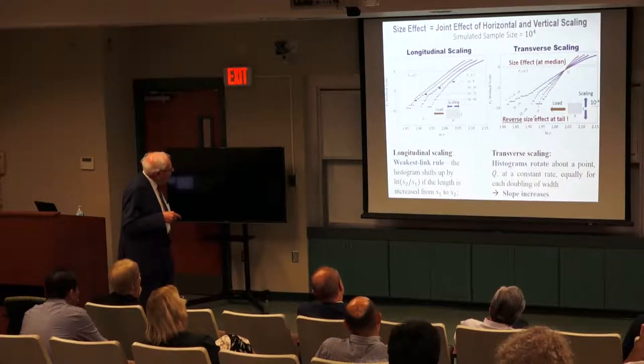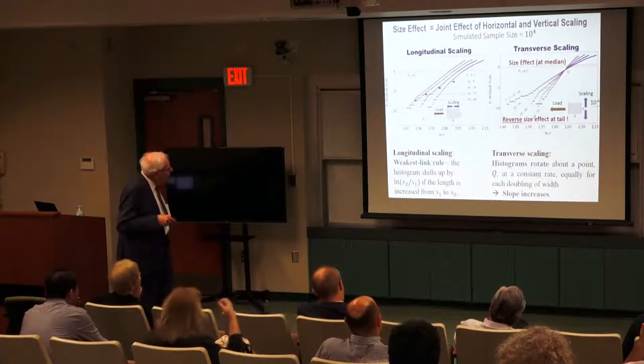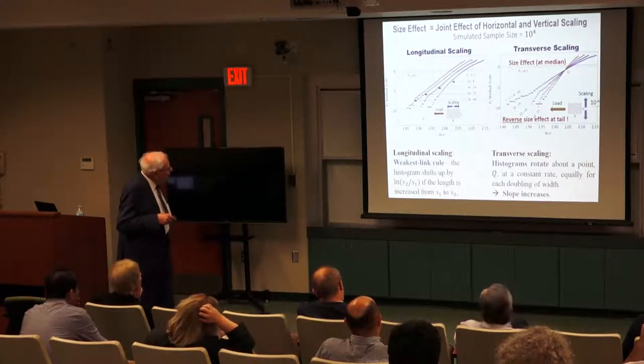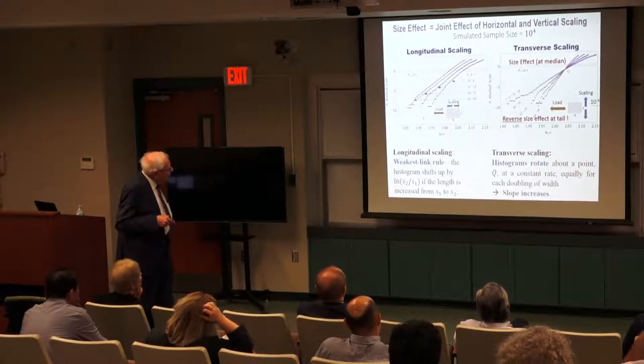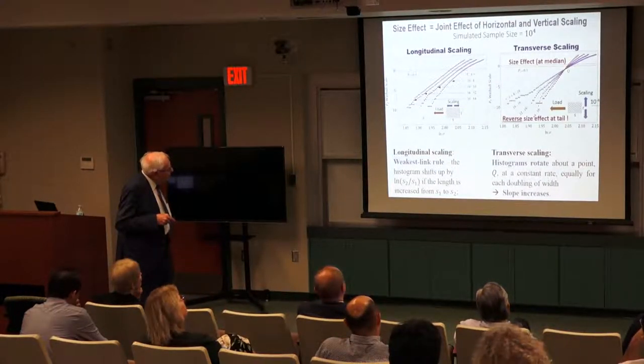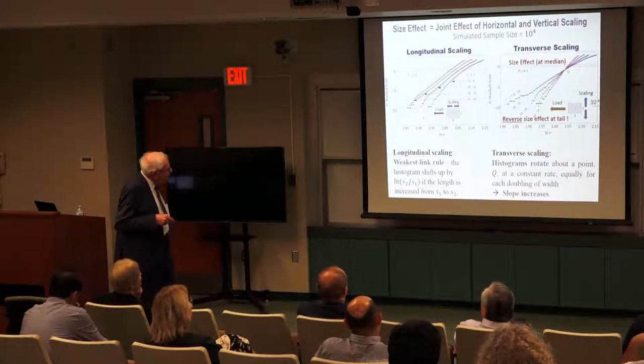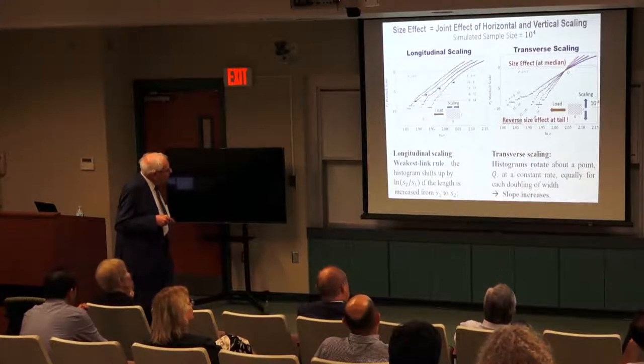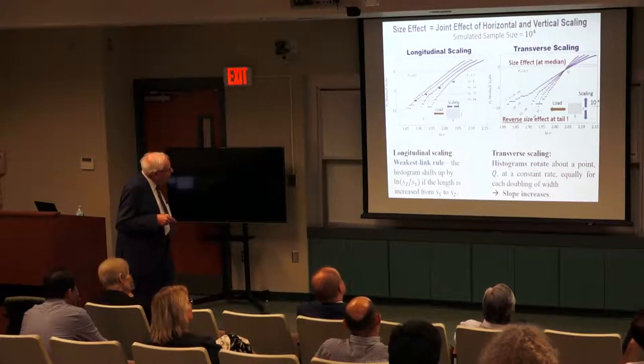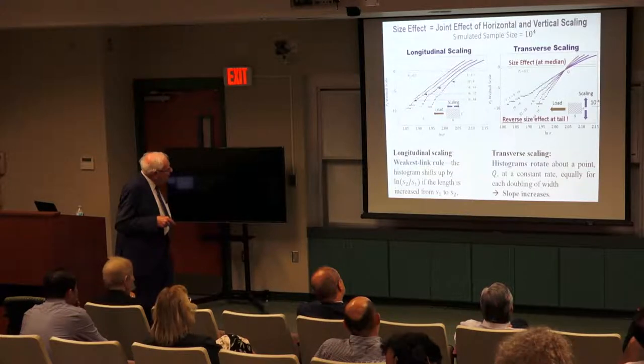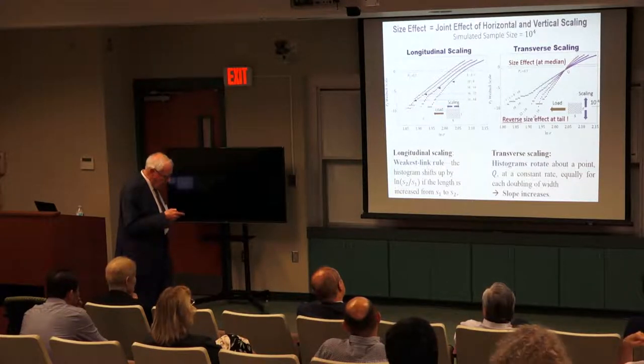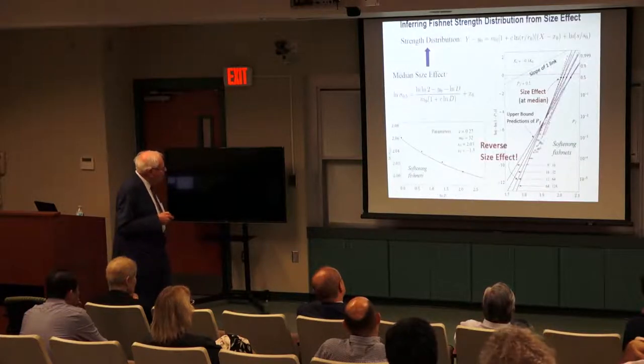Longitudinally, you see that in the middle you keep the same slope, same modulus, but it deviates earlier. And then actually we can put it into simple formulas. And if we do transverse scaling, interestingly, all the distributions rotate about one point. And I can actually show that it has to be about one point. So here you have positive size effects. Structure is bigger, it is weaker. But if you do the transverse scaling, the opposite happens. Now which one wins? You must put these two together. And if you put them together, you see this picture.